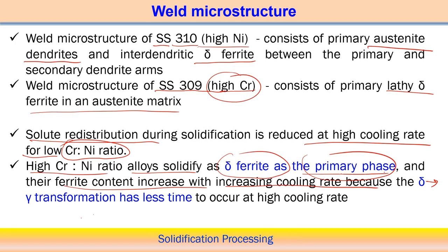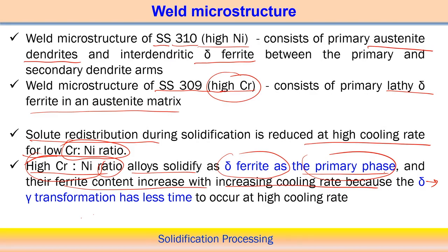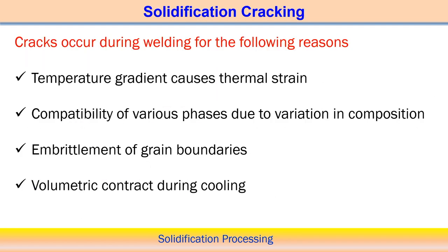So delta phase is the primary phase. Even if the cooling rate increases, the delta ferrite content also increases, but it is associated with a high chromium to nickel ratio. But it may not be true in the case of a high cooling rate when the chromium to nickel ratio is low. In that case, the solute redistribution may be more as compared to the high chromium to nickel ratio. So I mean to say that the solidification behavior in these two cases is different, and because the solute content is also different, we can get different morphology, different structure associated with the two different types of steel.